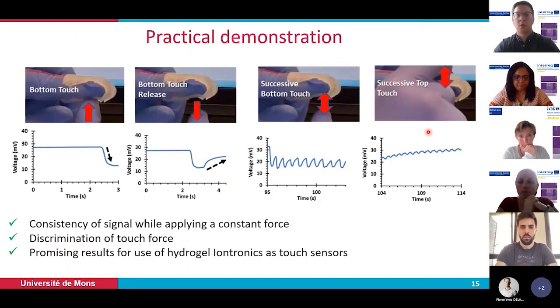Based on this result, we try a practical demonstration. We use our materials as a fingertip. And what we can see is that we have a direct response of the materials to the touch. We also have a consistency of the signal while applying a consistent force. If we look at these two graphs, we can see that we have two really different signals if we use a big touch, high pressure, on the left and a small touch on the right. So you can really discriminate the touch force, which is really interesting. These are promising results for the use of hydrogel iontronics as touch sensors.